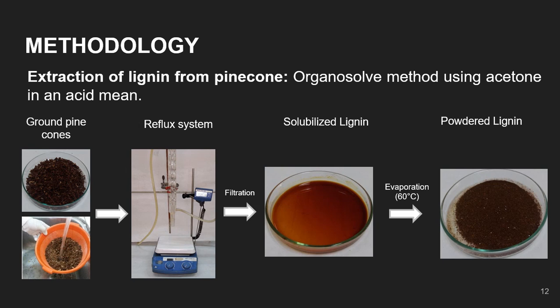Regarding the organosolve extraction method, after pre-treatment of the biomass, the crushed pine cones were placed under reflux system for 24 hours, using acetone as an extraction solvent in an acid medium. The solubilized lignin was separated from the solid residue, and its solvent was evaporated. As a final product, lignin was obtained in powder form.